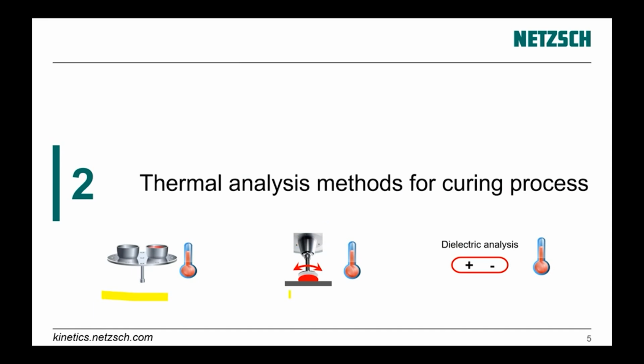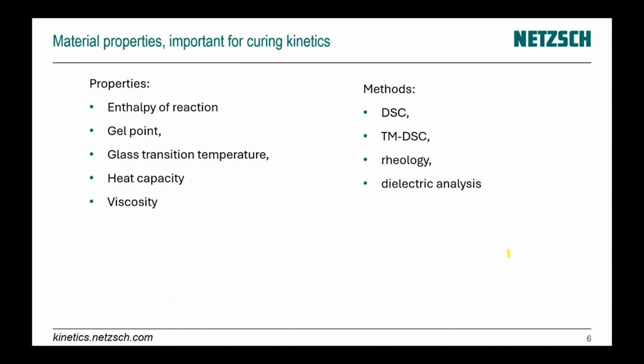It is DSC, it is a rheometer, and this is dielectric analysis, where we can measure the ion mobility of dipoles and how they rotate under an applied electrical field. Here, for kinetic analysis we usually need the enthalpy of reaction, gel point, glass transition temperature, heat capacity, maybe viscosity. The methods used to measure all these properties are DSC, temperature modulated DSC, rheology, and dielectric analysis.